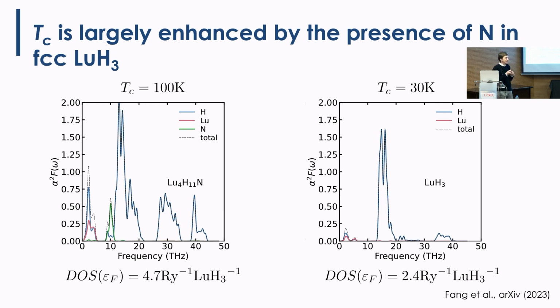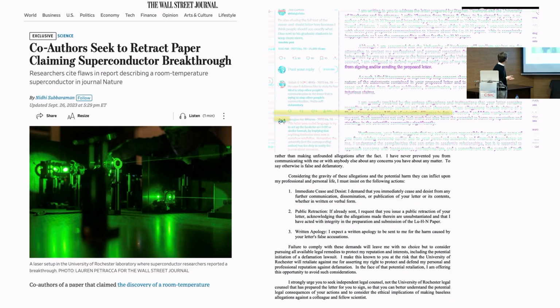So here, basically, what I'm saying is that when we are adding this nitrogen, something is happening that is increasing the critical temperature here. That's for sure in this compound, even if this is not thermodynamically stable. And the reason is in the electronic properties. So you can see the density of states at the Fermi level is increasing a lot. It's basically doubling when we include the nitrogen. So chemically the things are changing. And somehow, to me, this is saying, I don't know, I don't think we are explaining at all the experiment here, no. But I'm saying here that maybe there are some hydrides that actually, with doping and engineering things, can give high TC values at low pressures, okay? So basically, this is it, okay?